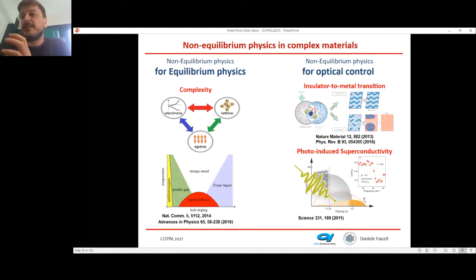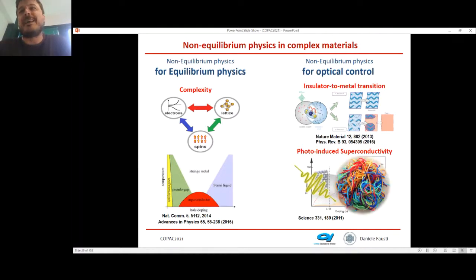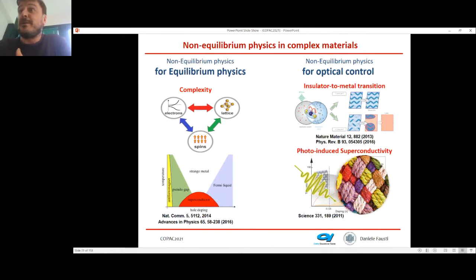And if you think about it, the situation is kind of counterintuitive, because if I want to recast this example with my bundle metaphor, it basically means that I start from a very disordered interaction between all the constituents of matter, and by photoexcitation I get a nice pullover. And it's a very lively research field: how does the electric field trigger the formation of a low entropy state? And here I cite only my own works, but there are many others.